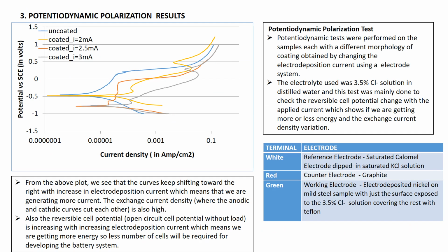Next, we come to the potentiodynamic polarization tests, which were performed for different morphologies of coatings by changing the electrodeposition current as done earlier. The electrolyte used was 3.5% Cl minus solution, and we used these electrodes as given in the table, such as reference electrode, counter electrode, and working electrode. From the plot, we can see that the curves keep shifting upwards towards the right with increase in electrodeposition current, which means that we are generating more and more current, and the exchange current density is also very high. Also, the reversible cell potential increases with increasing electrodeposition current, which means we are getting more and more energy. So effectively, a smaller number of cells are required for development.